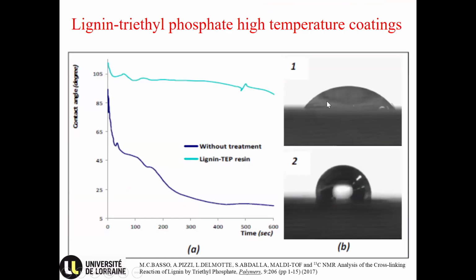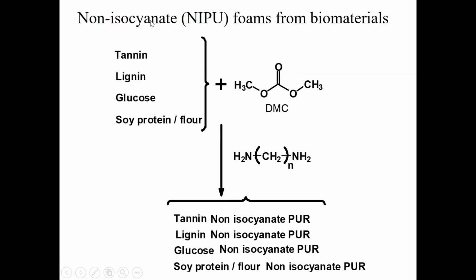You can see the contact angle of the drop when the system is not used and when the system is used, without treatment and with the lignin triethyl phosphate treatment. You see it is very good. You can see it maintains very well. That is free for all. It's not patented. Then we graduated to non-isocyanate foams and adhesives from biomaterials.